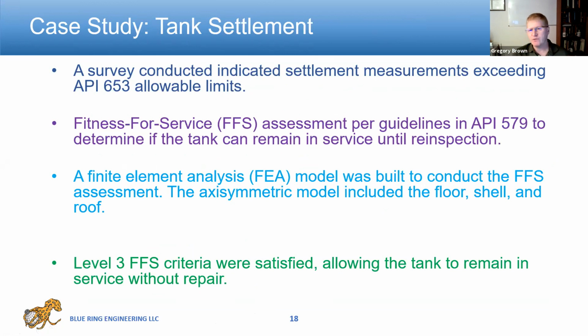This same type of analysis is very often used for other tank assessments. For example, if you have a repair on a storage tank, you're usually required to hydrotest that tank. Now, what is a hydrotest? You fill the tank, you hold it, you make sure it remains stable. This can be very expensive to conduct. So what we can do is we can use the rules in 579 to actually give you an exemption for a hydrotest. So what that means would be we use some analysis, we look at the inspection that was done of the repair, of the welds, etc. We make sure that any flaws that exist in those welds would still be stable and acceptable. If you meet those requirements, then you are actually exempt from the hydrostatic testing, which can be very, very significant cost savings. We'll talk about hydrotest exemptions in the course as well.